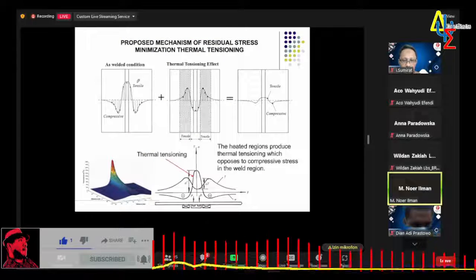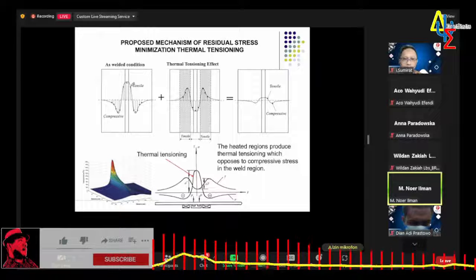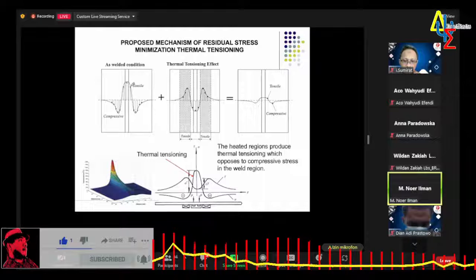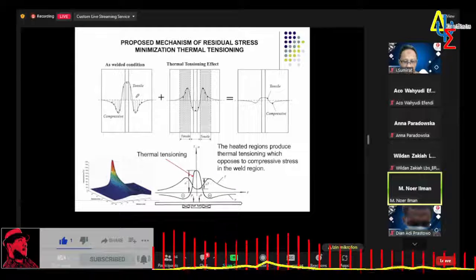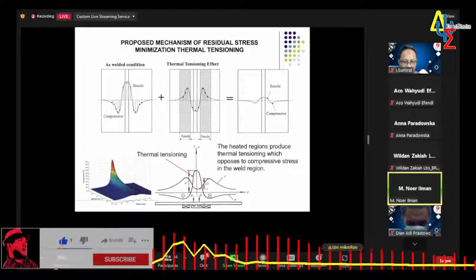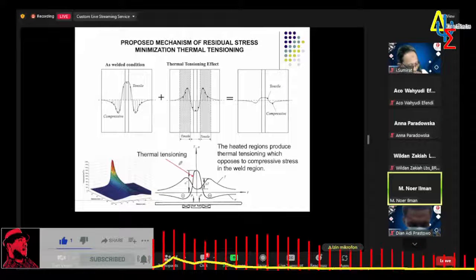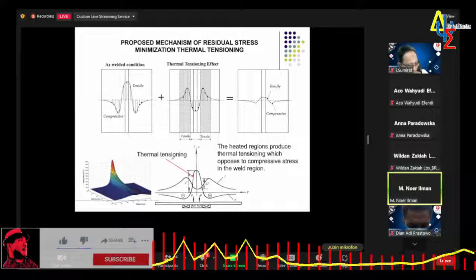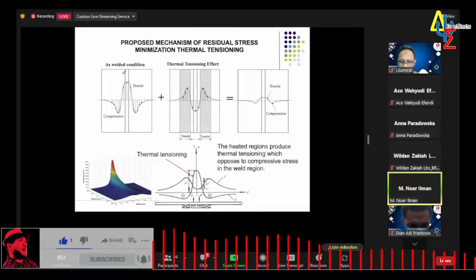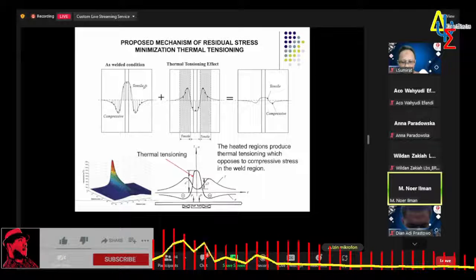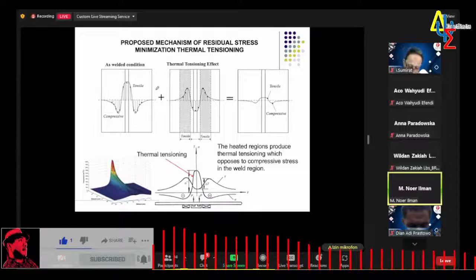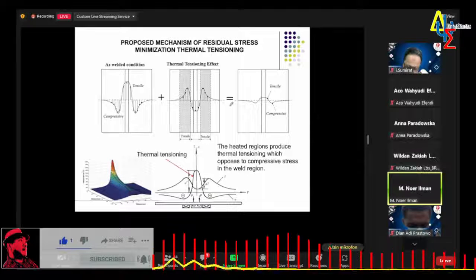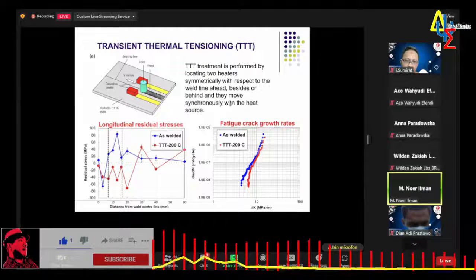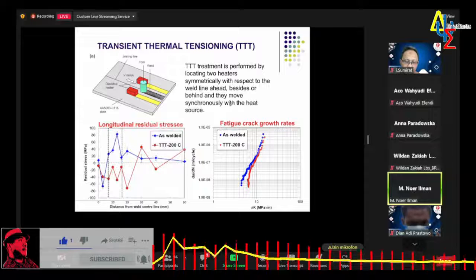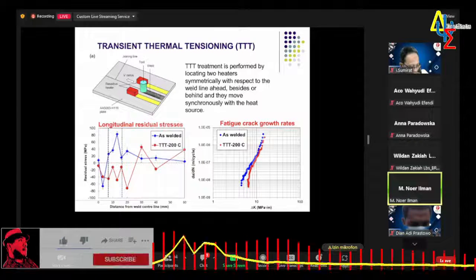And then this is the mechanism of how TTT can minimize welding residual stress. Actually, the introduction of local heating here produces what we call thermal tensioning, and thermal tensioning opposes the shrinkage stress caused by the weld. So the resultant of the stress load will minimize each other. And then next we developed transient thermal tensioning (TTT) treatment, and we located two